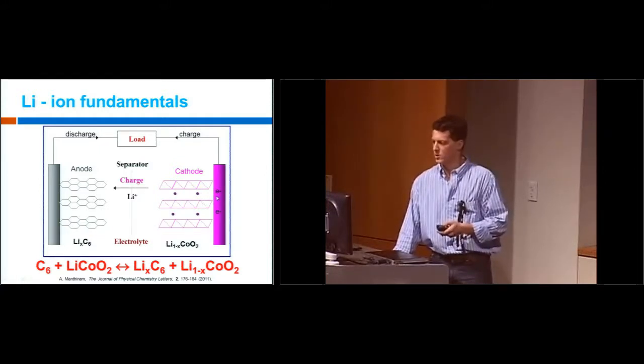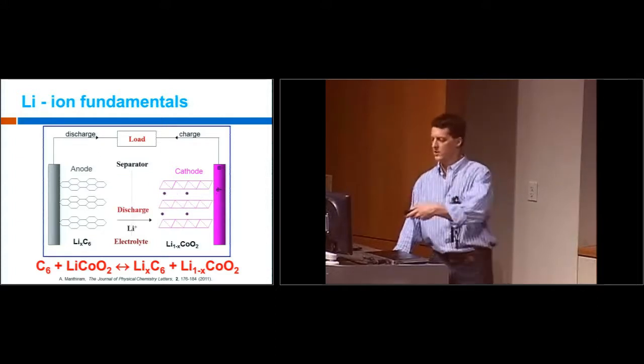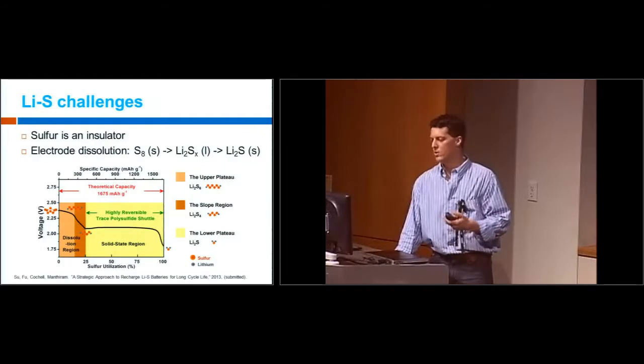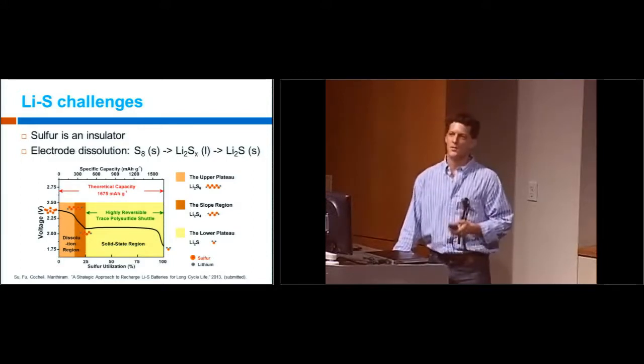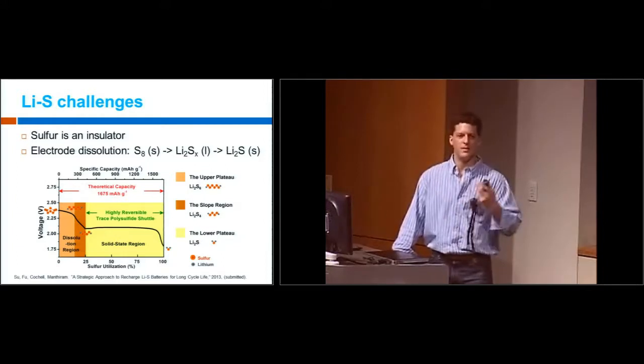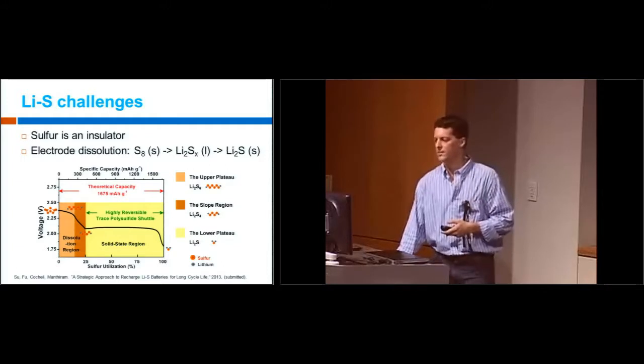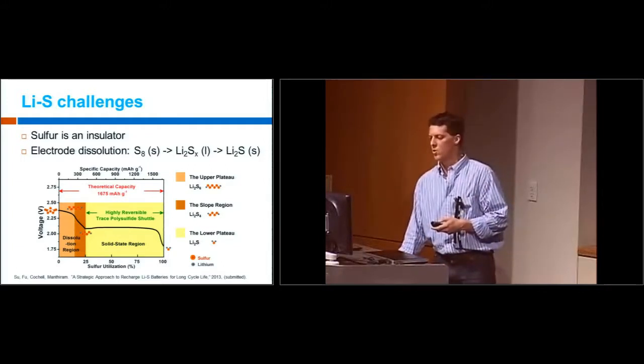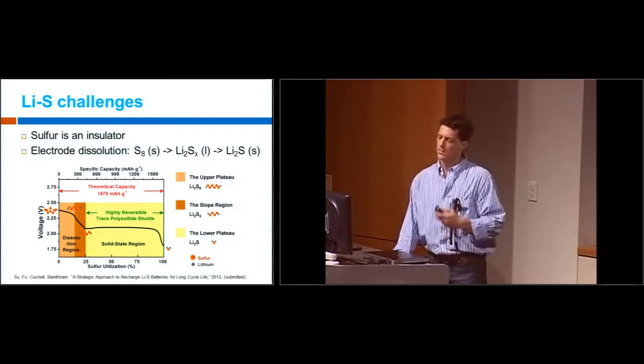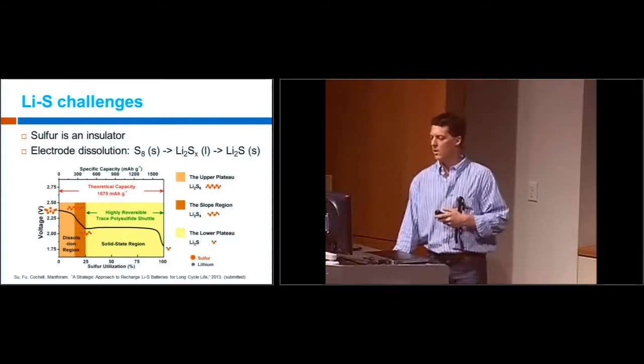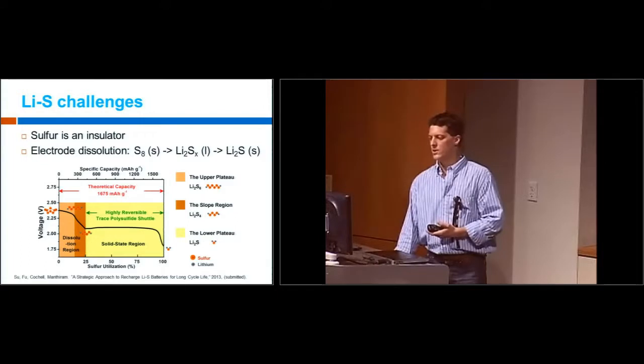This is just an illustration of the charging process, and then the discharge, where you can see the lithium shuttles back over. By contrast with sulfur batteries, sulfur is an insulator, which makes it very difficult to use in a battery material where you need electrical conductivity because you're extracting the electrons out of the material to provide the energy. This gives rise to a whole bunch of challenges. The other thing is that whereas the state-of-the-art lithium-ion batteries are all solid state, the sulfur involves a transition from the solid form, the elemental sulfur at the beginning of discharge, to liquid lithium polysulfides, and then finally becoming solid again.